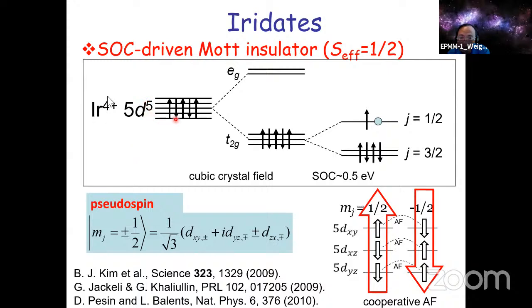iridium. This iridium 4+ has 5D electrons upon large crystal field splitting. So you have T2G orbitals that are effective, and then upon this large spin orbital coupling splitting, we have those low-lying fully filled total angular momentum 3/2 states, and this effective 1/2 pseudo spin state. This forms a narrow band near the Fermi level. And what's special about this pseudo spin state is that you have a composition of different orbitals. You have 3 T2G orbitals right here. So this internal degree of freedom will open a pathway to novel exchange pathways.